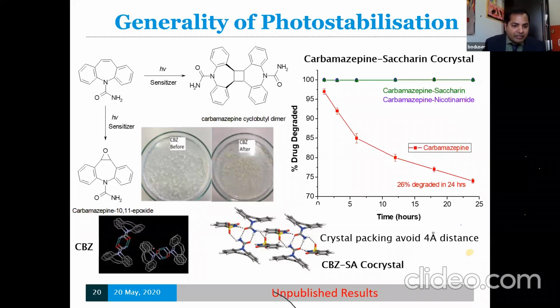If you look at the crystal structure of carbamazepine in the bottom left, you could see the arrangement of carbamazepine molecules. Because of the close stacking arrangement, if the distance is about 3.6 to 4 angstrom, then you could expect this photodimerization. So what we did was, we already had these results by then, which still need to be published. We know that the crystal structure of carbamazepine saccharin was published way back in 2003. When you look at the crystal structure with saccharin, saccharin has altered the crystalline lattice of carbamazepine.